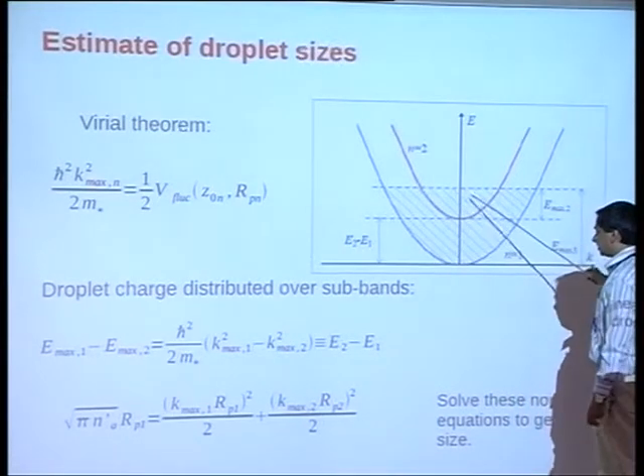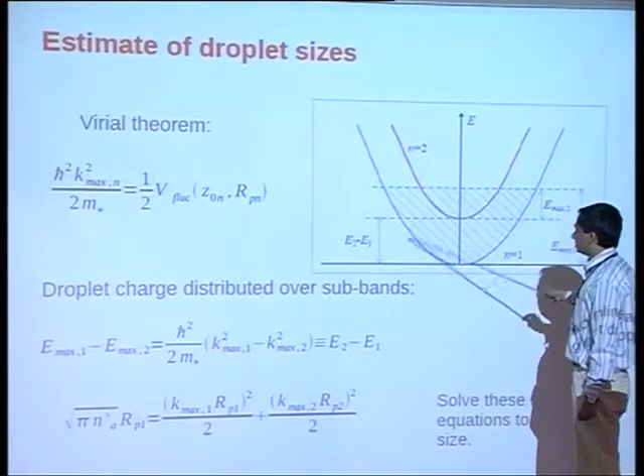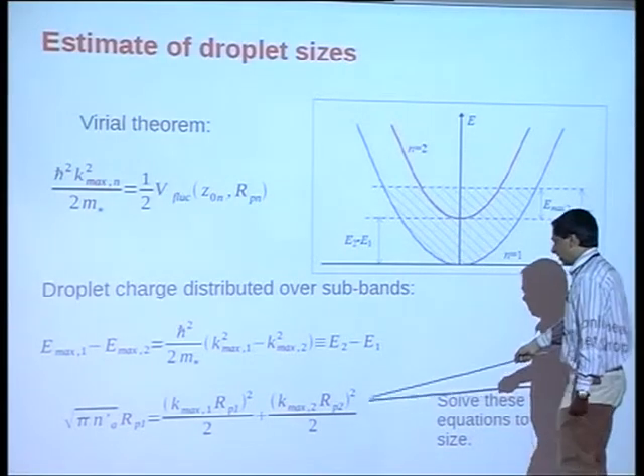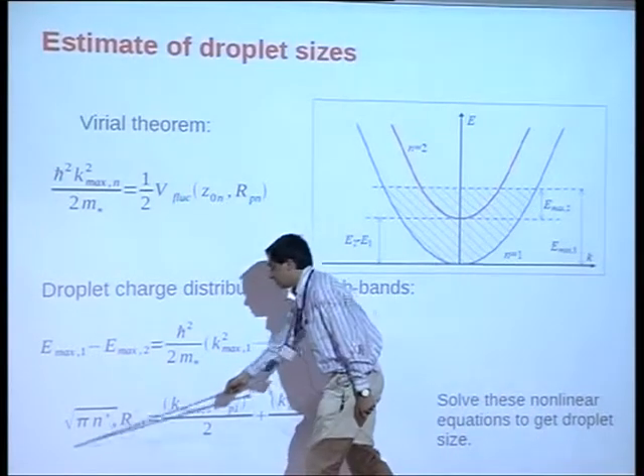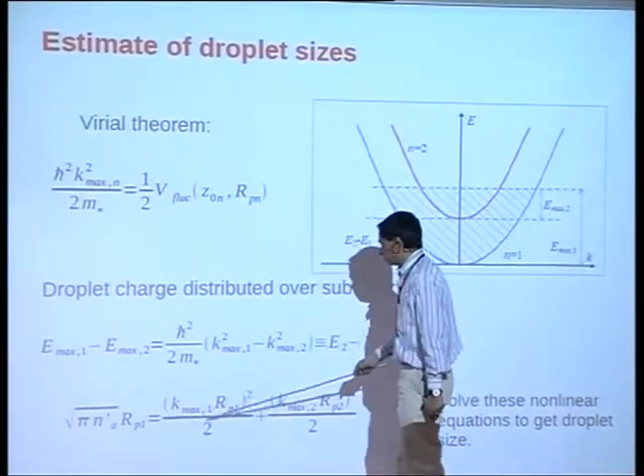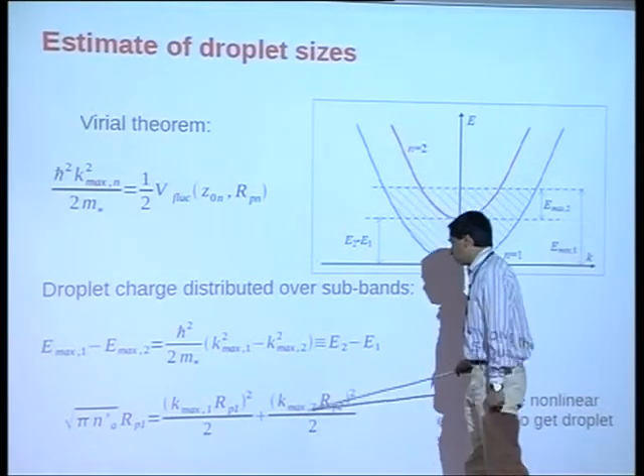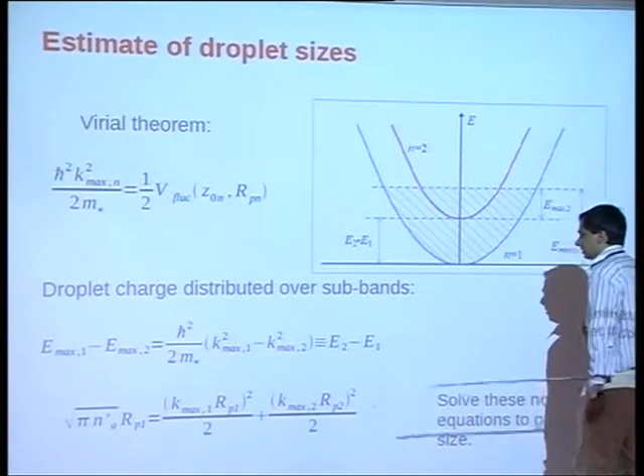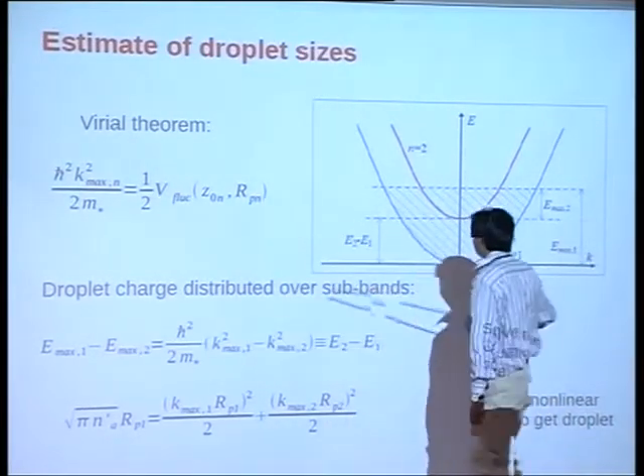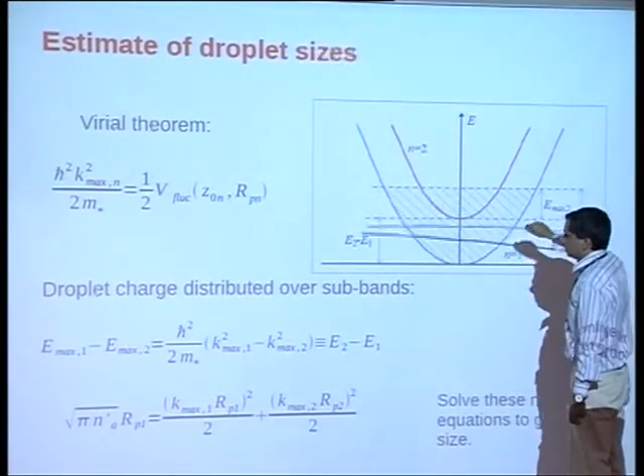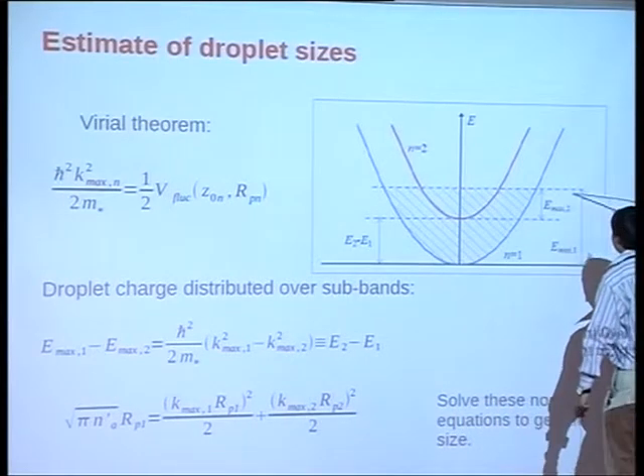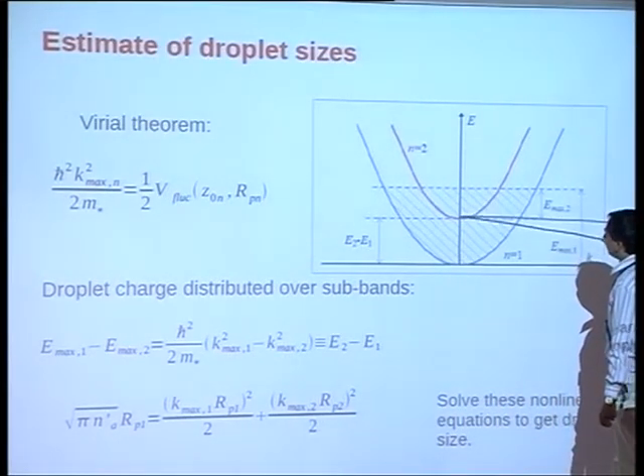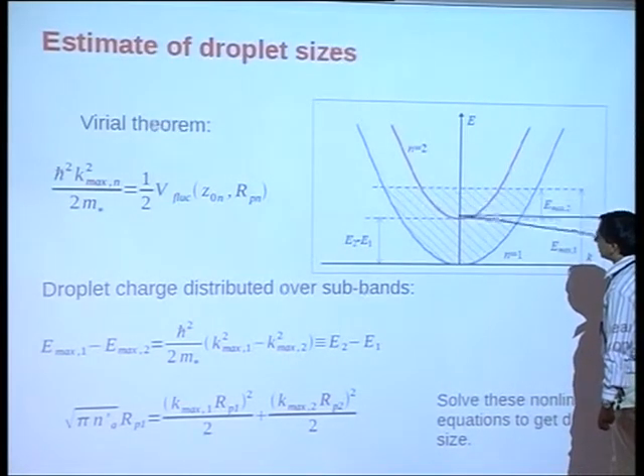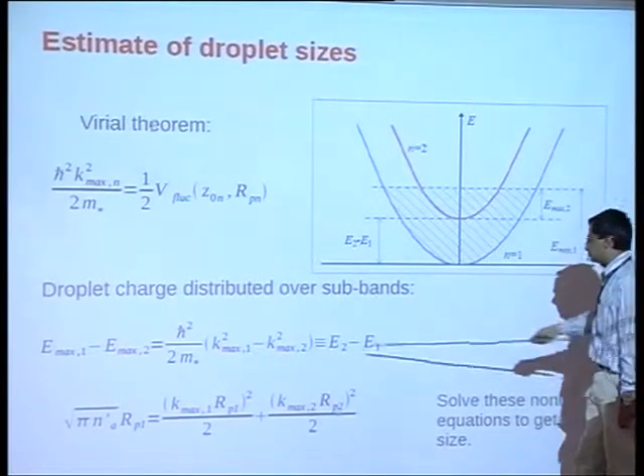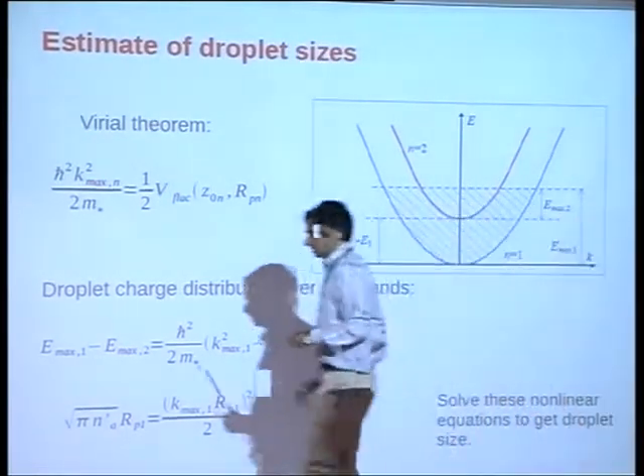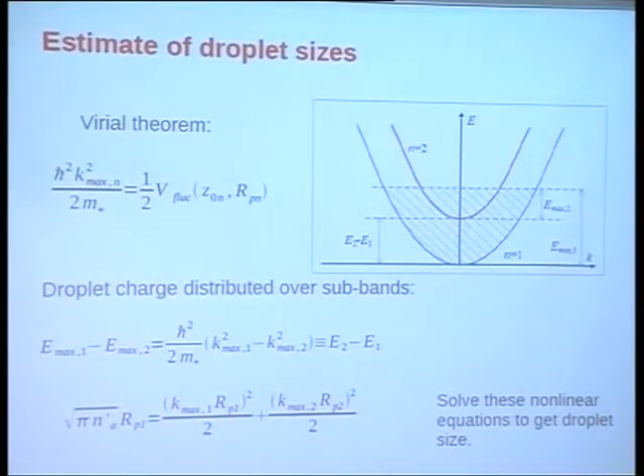Now, when I have 2 subbands, I can say that the droplet charge is distributed over these 2, and the lower equation shows that the total charge in the droplet, which is the fluctuation charge at this length scale, is distributed over these 2 subbands. So the charge in the 2 subbands, I just add them up together. And this one shows that the difference in K maxes, for the quantum well of subband 2, it is a much smaller K max than for subband 1. The difference is just E2 minus E1, the difference of binding energies at K equals 0.